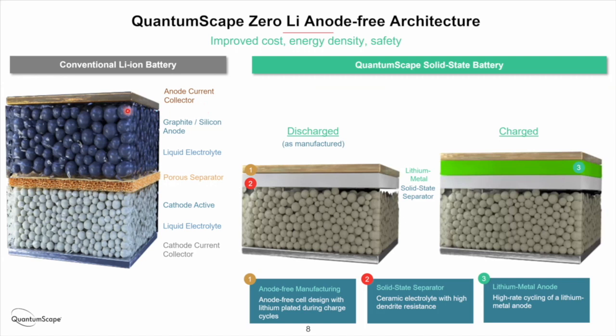So this then shows the lithium ion architecture in comparison with the QuantumScape architecture that we have, where we have what we call an anode-free design. So there is no anode in the as manufactured state. We have a separator that interfaces to a current collector and nothing present in the anode side. The cathode is relatively similar, both the active materials and ion conductors or catholyte inside the cathode share a lot in common with lithium ion batteries. But we've replaced the anode with nothing in the manufactured state. And then all the lithium that's in the cathode material as manufactured will, on the first charge, come and plate at this interface between this separator and the current collector and form this block of lithium metal at the anode side. And then this is the lithium that cycles back and forth as you charge and discharge the cell.